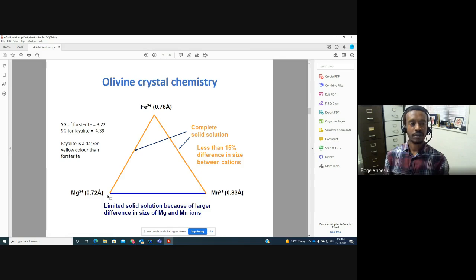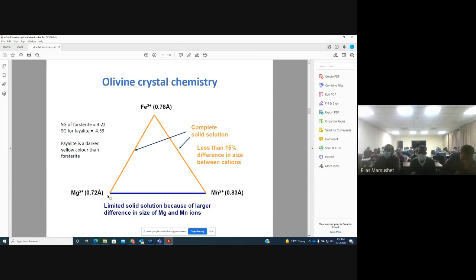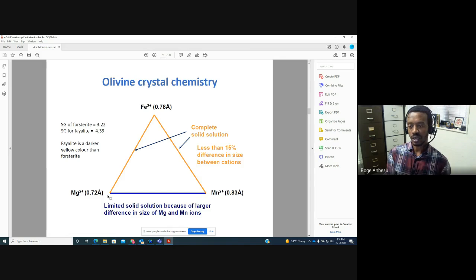So what is the fuss about solid solutions? Why do we care about knowing about solid solutions? Because based on how much iron replaces magnesium, olivine, in this case, can be lighter or denser. Okay, for example, specific gravity of pure forsterite is 3.22. Specific gravity of fayalite is 4.39. If you have more iron replacing the magnesium, the olivine becomes heavier and heavier. So in this case, solid solutions can affect specific gravity.